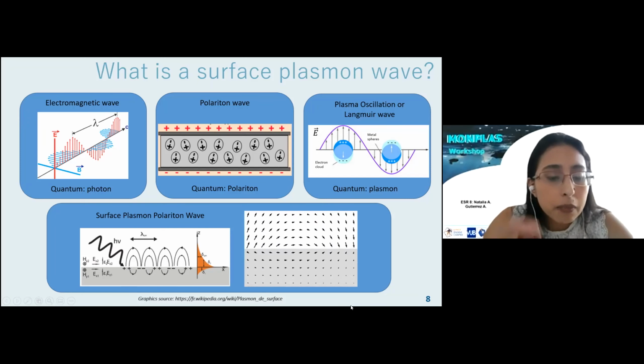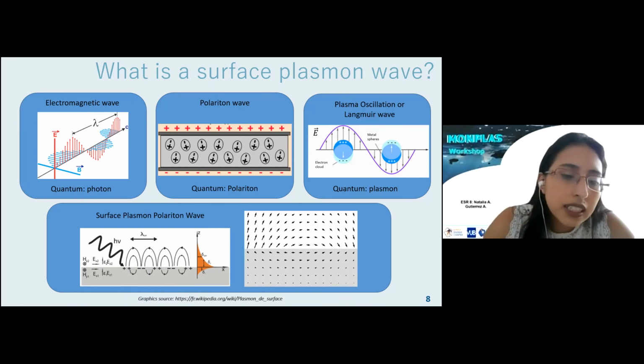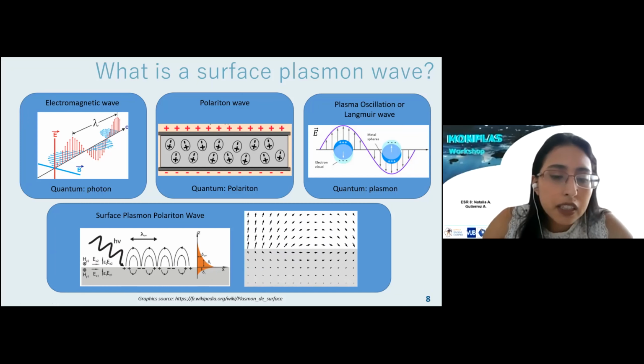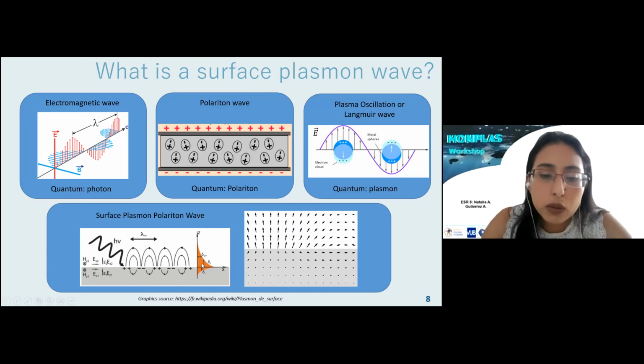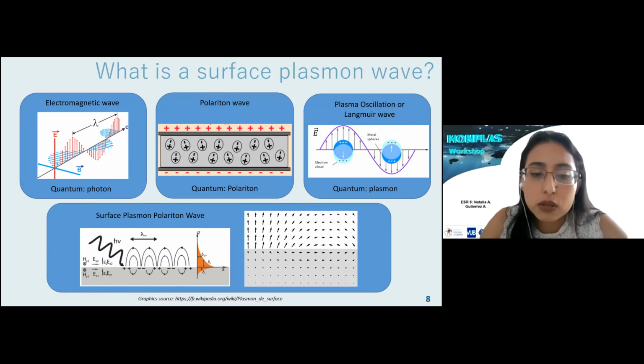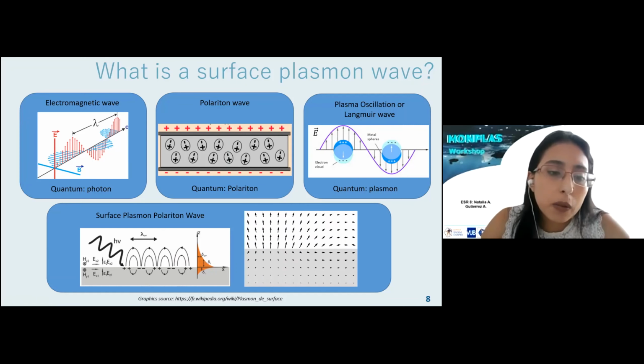What is important here also is that there is a penetration depth inside the dielectric medium, and this depth is going to give us the range where we are going to be able to measure inside the dielectric. And this depth goes between 200 nanometers up to 10 micrometers, depending on the wavelength that we are using to excite the plasmons.